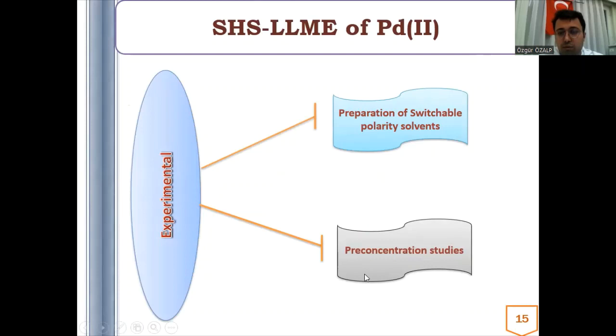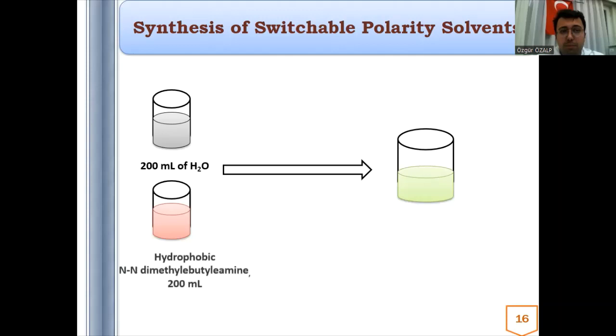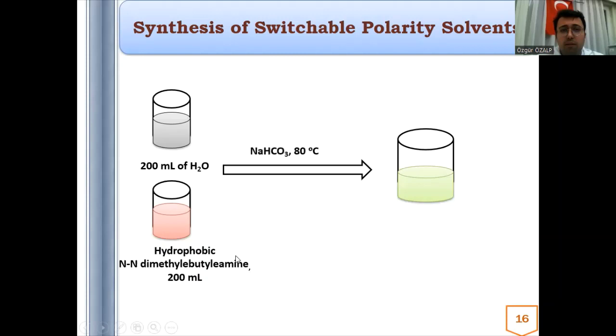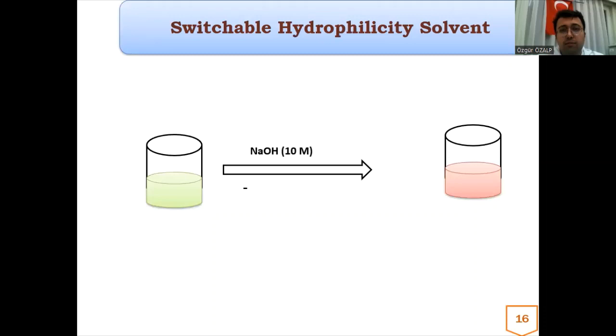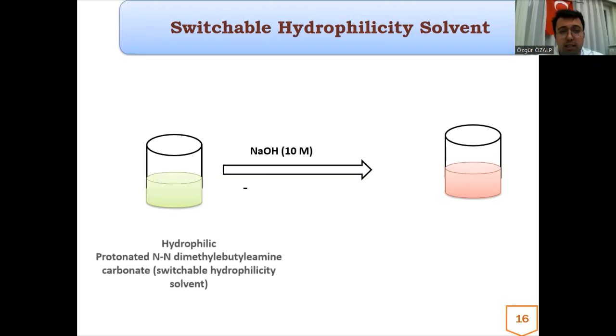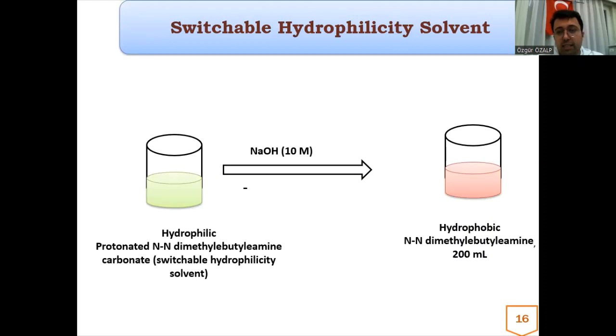For the synthesis of the switchable solvent, you can see one cup containing 200 milliliters of water and 200 milliliters of N,N-dimethylbutylamine. To start the reaction, we add carbon dioxide, using sodium bicarbonate, at a temperature of 80 degrees centigrade. Lastly, we obtain hydrophilic protonated N,N-dimethylbutylamine carbonate, totally 400 milliliters. For the polarity change, starting hydrophilic and lastly hydrophobic, you add sodium hydroxide at a very high concentration, approximately 10 molar. The extraction yields and pre-concentration are very high, and carbon dioxide is removed.